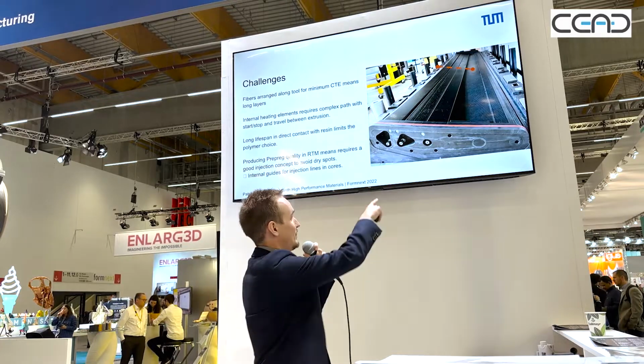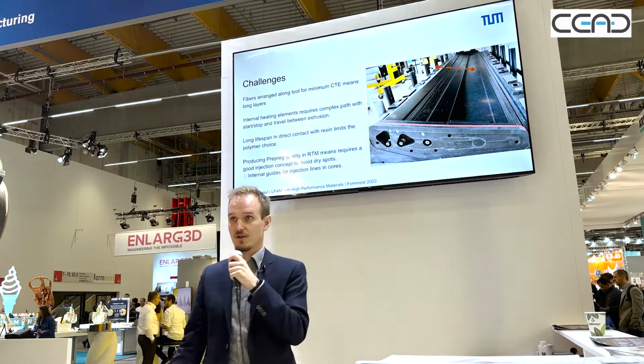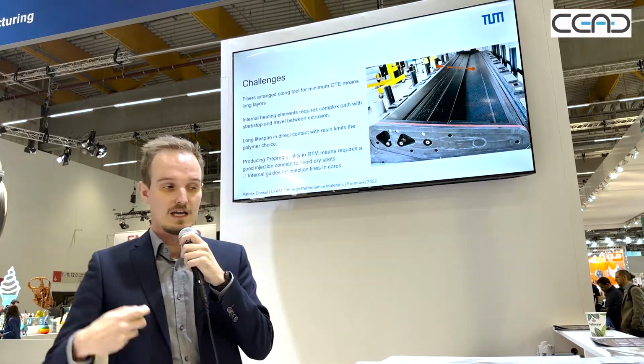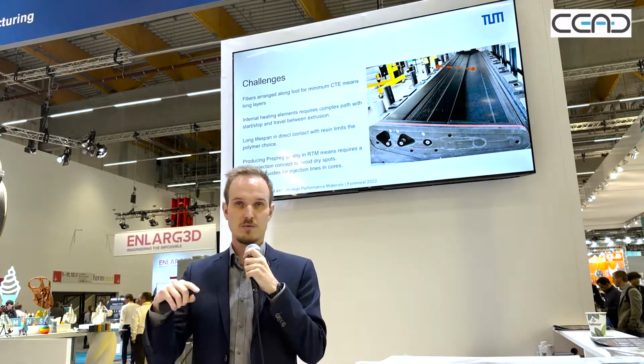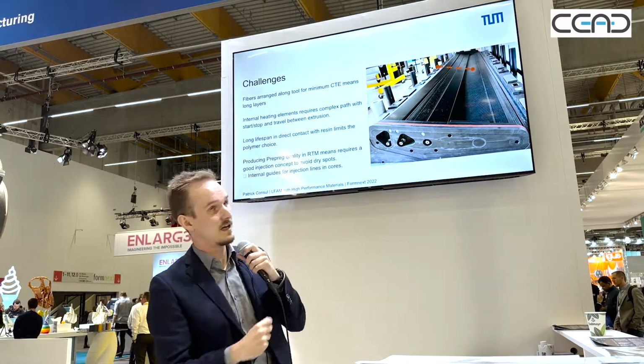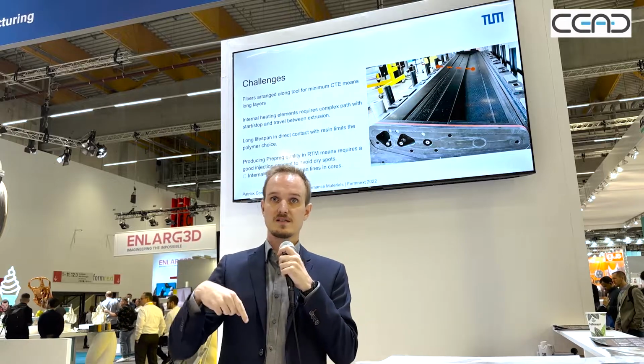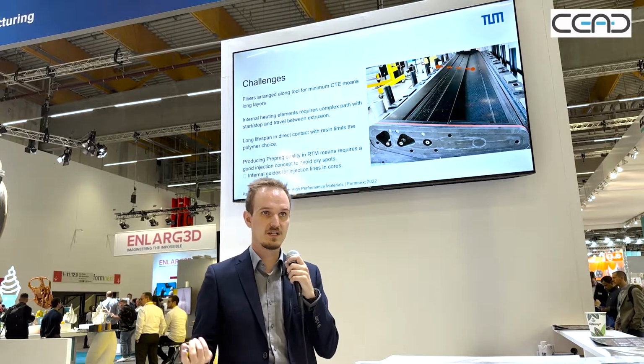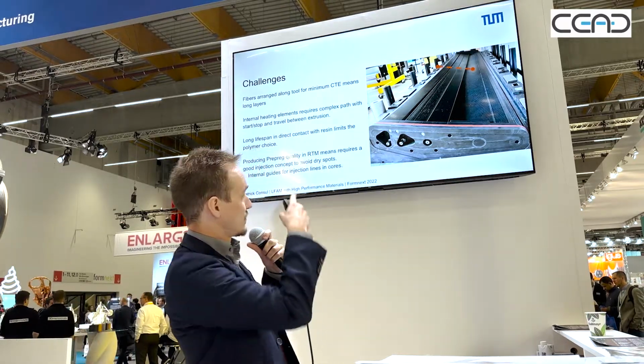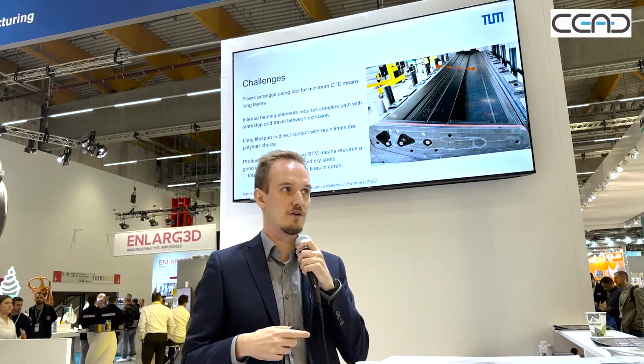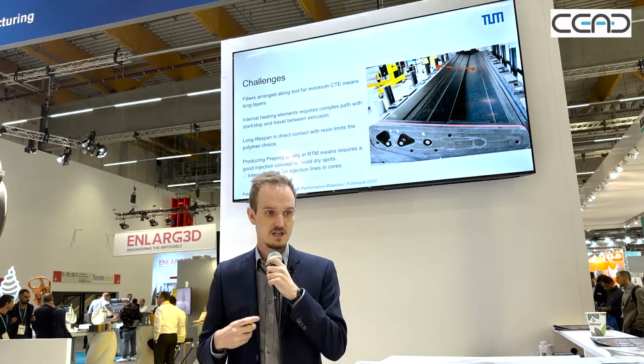You have these connections here. So the cores are actually hollow, and you can push the injection lines all the way through the cores to the dotted line, and then you fill the part from the inside out, something that's not possible with metallic tooling, where you have the parts machined from a block. First of all, because the cores are about 1.5 meters in length, and second of all, they're slightly curved.